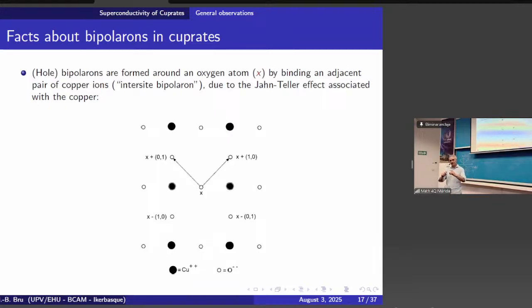So when the electrons move, or the electrons are all fermionic particles. In fact, it's holes, it's not electrons. They move in this two-dimensional layer, and typically it is experimentally shown that they move inside the oxygen, not in copper. So this is the oxygen, this is the copper. On the other hand, sometimes they go to the copper, and they are trapped with this Jahn-Teller effect, which produces a deformation of the lattice, and it forms a quasi-particle which is called a polaron. So that's the concept of polaron.